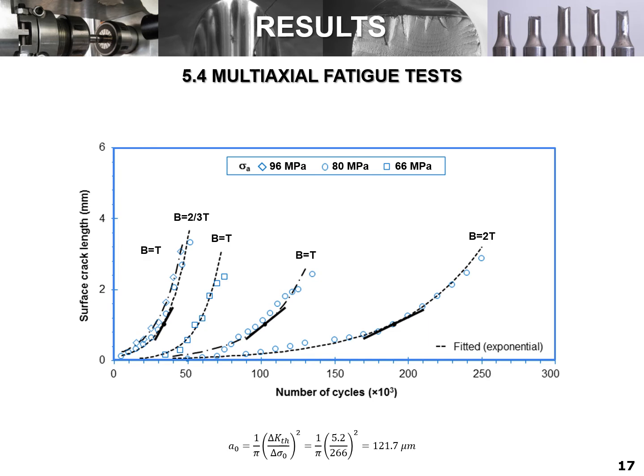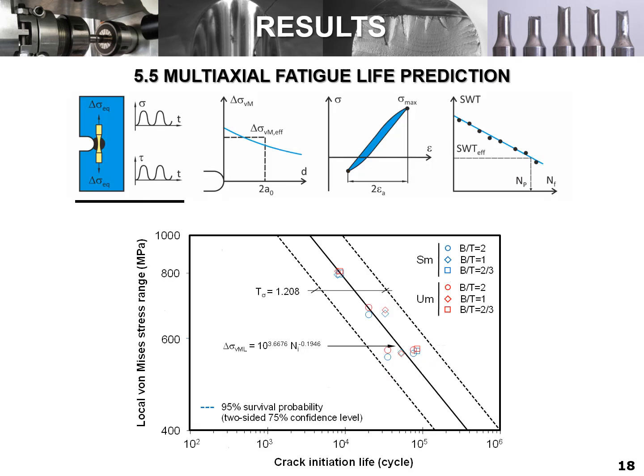The experimental fatigue lives were determined from the S-N curves. Since the fatigue process encompasses the initiation and growth of 2 cracks, 2 S-N curves were obtained for each test. In the figure, we can see the curves obtained for the first crack to appear in the specimen. The data, regardless of the bending-torsion ratio and the nominal stress amplitude, were successfully fitted by exponential functions, represented by the dashed lines. Using these curves, we calculated the number of cycles to crack initiation, assuming a crack length equal to the material characteristic size. After the calculation of the experimental lives, we can test the predictive capabilities of the proposed method.